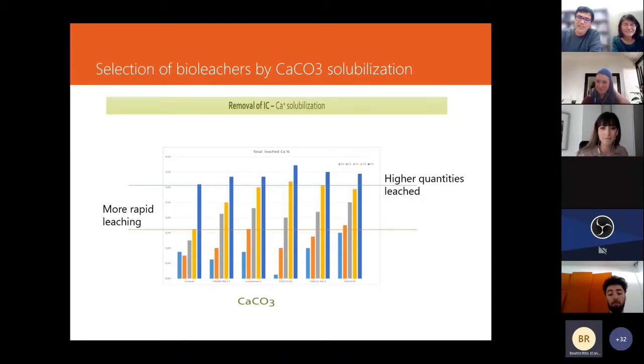So first, we performed a test on calcium carbonate directly, and we tested one representative strain of each of the genera that were isolated, and we selected the strains that managed to leach calcium more rapidly and to a higher extent. So we ended up with a selection. Next slide, please.